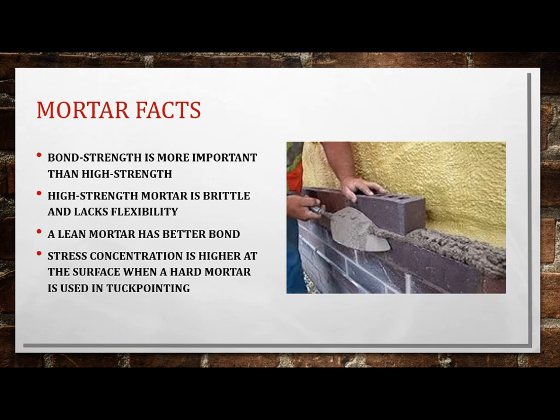Some facts about mortar: bond strength is more important than high strength. High strength mortar lacks ductility, it's brittle, it will not flex, it'll crack before flexing. A lean mortar has better bond and is more desirable. When you're tuck pointing, if you use a very stiff mortar, it actually puts more stress concentration on the face of the wall and can lead to face cracking of the brick, because it's stronger at the face than it is in the rest of the bed joint.